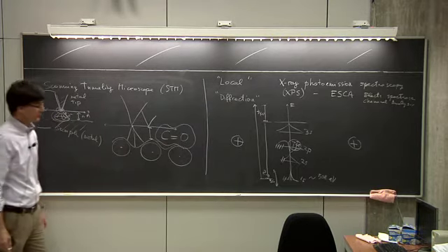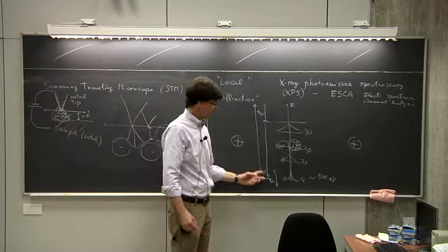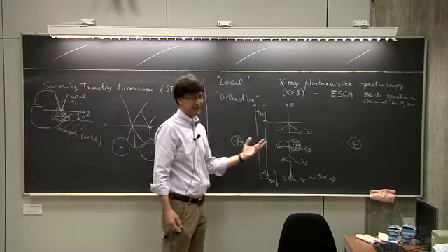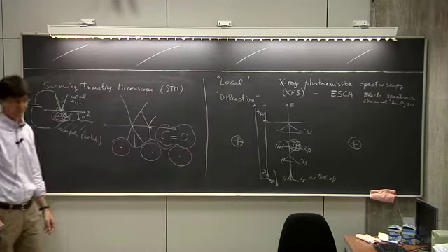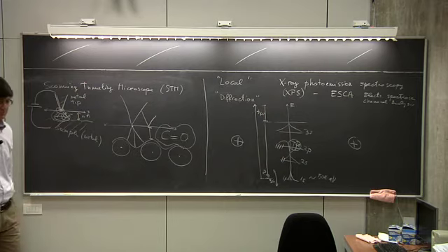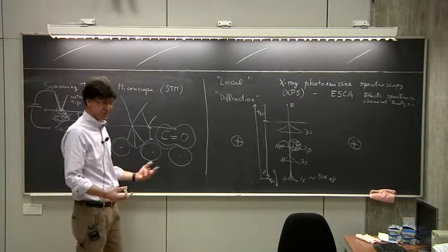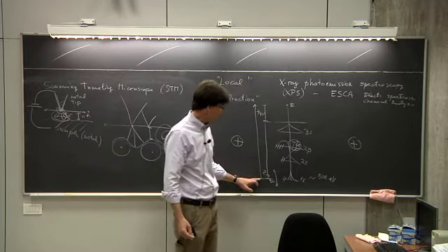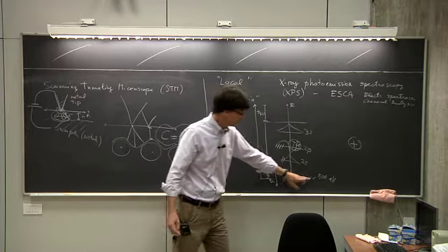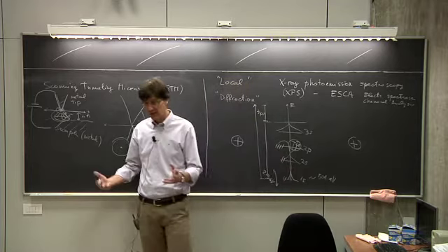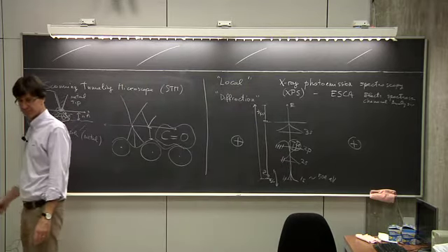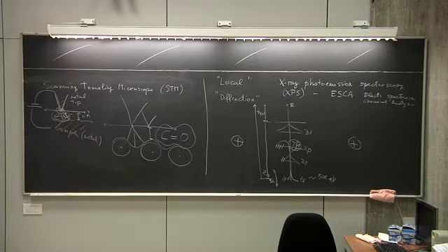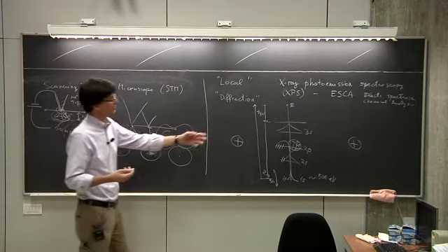Okay? And depending on your result, you can then study the environment of your system, of your atom in the crystal. The oxidation state, for example. Of course, to do that, you require photons in the kilo-electron volt range. Okay? So these are X-ray photons, typically. That's why this is called X-ray.